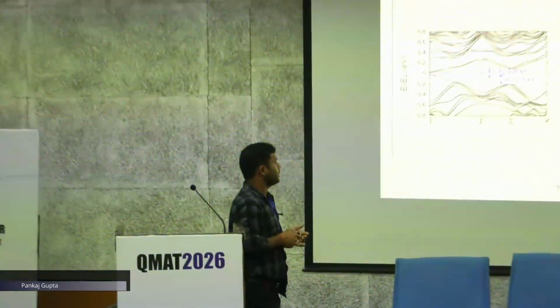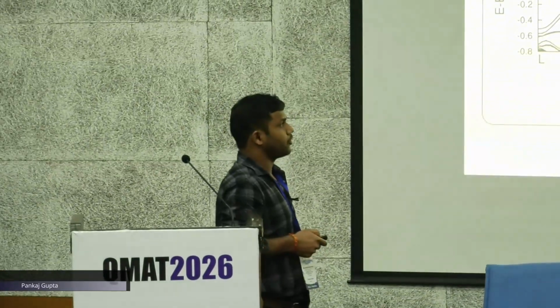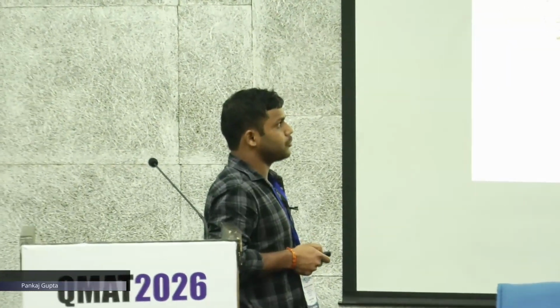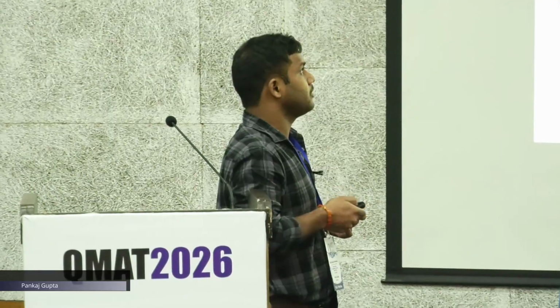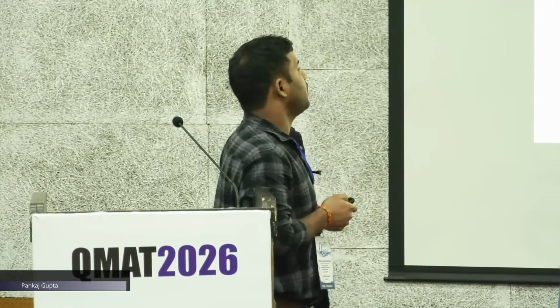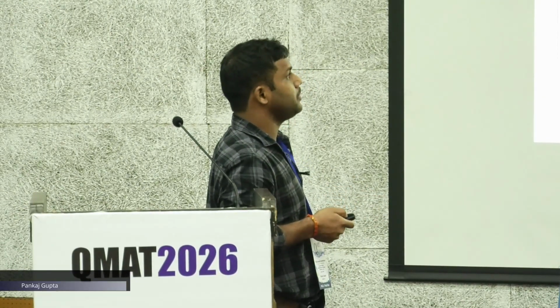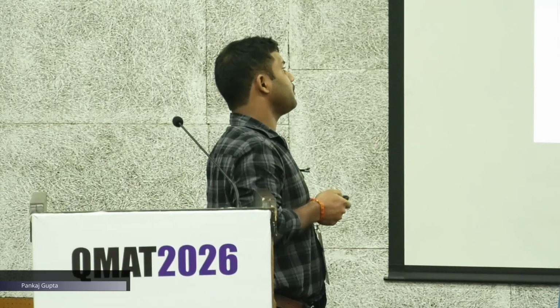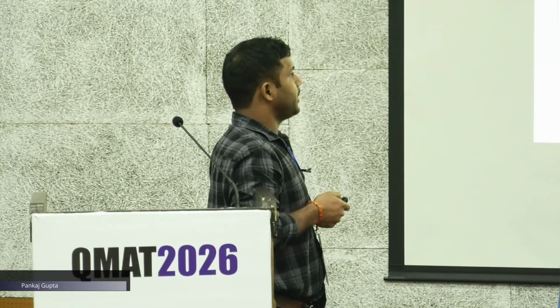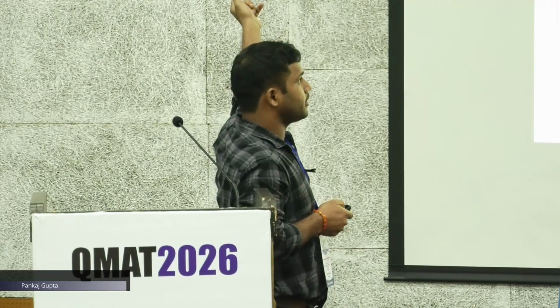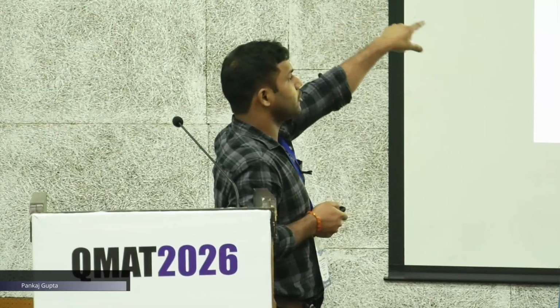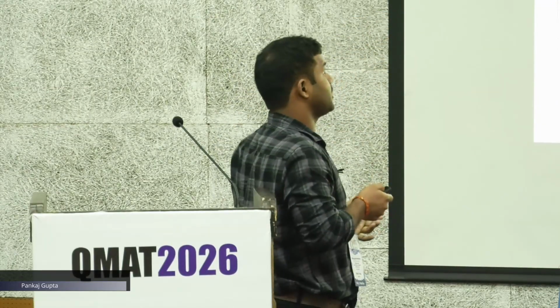So for that purpose we came to a literature where people have reported that AgSbTe2 alloying reduces the thermal conductivity a lot, from nearly 2.5 to 1. So we thought to incorporate this effect in our sample as well. And at the same time, AgSbTe2 alloying has been reported to bring band convergence. Earlier this band offset was 0.3 in SnTe, if you remember. Here it is reduced to 0.16, meaning more band convergence can bring more density of states.